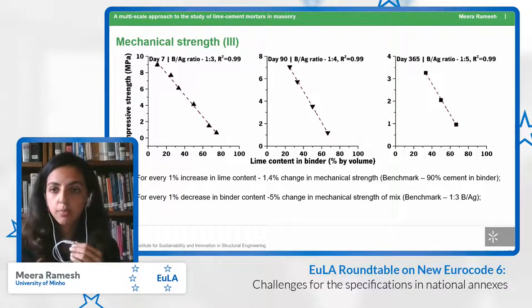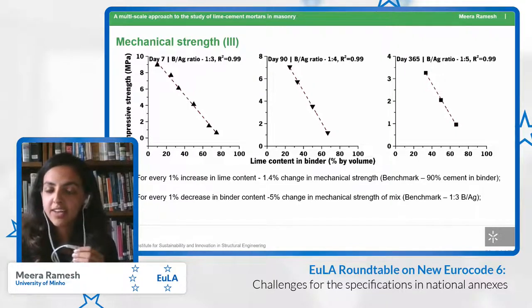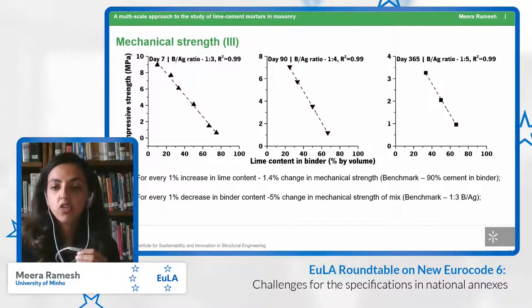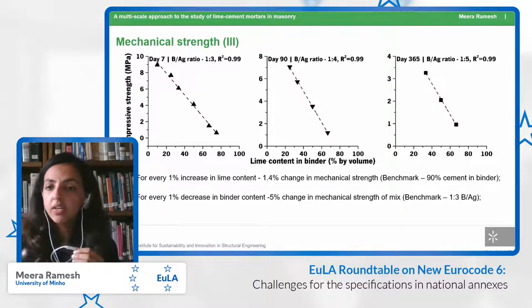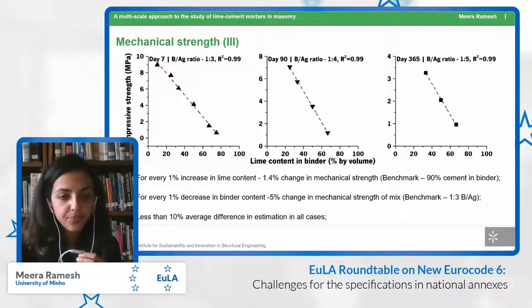In both cases, we had specific benchmarks, because you have to test one mix at least to normalize it. For the case of lime content, we had 90% cement in the binder as our benchmark because we needed at least some amount of lime in the mix to call it a lime cement mix. And in the case of binder aggregate ratio, we had 1:3 as the benchmark because that is the most realistic scenario of a strong mix that would be used on site, because 1:2 would be slightly unrepresentative.